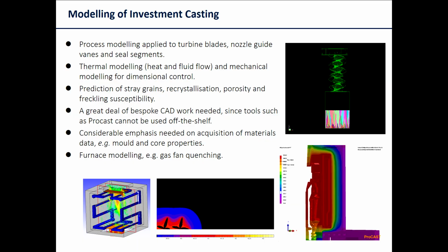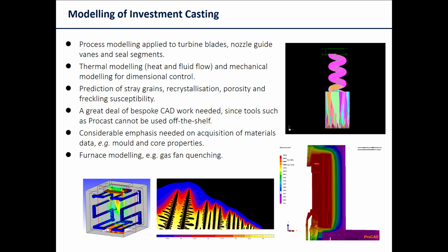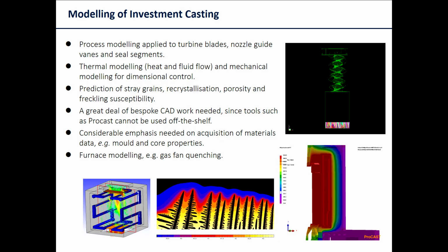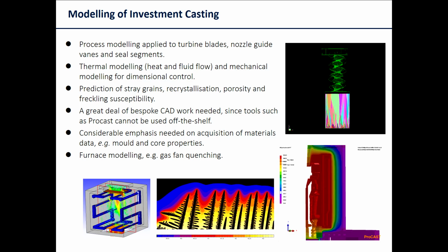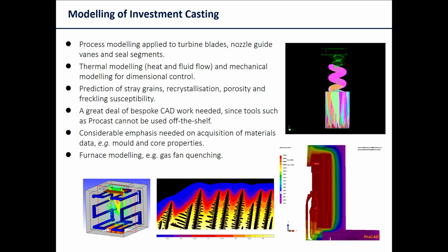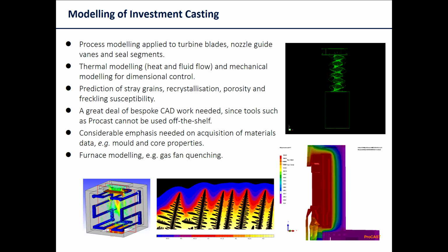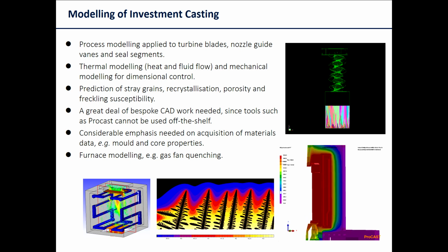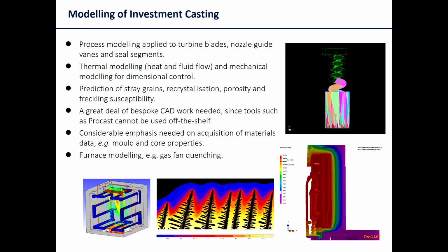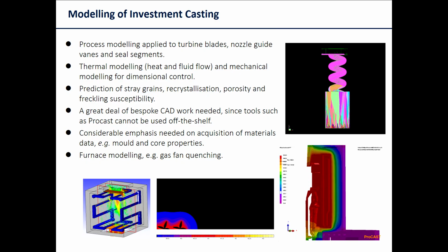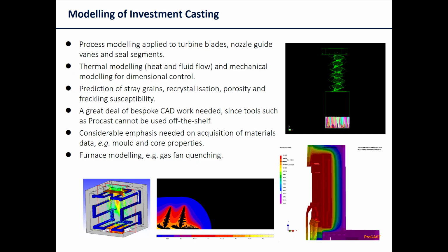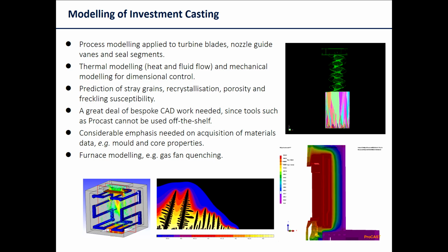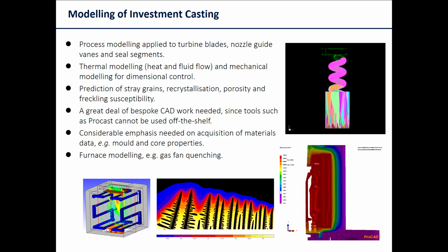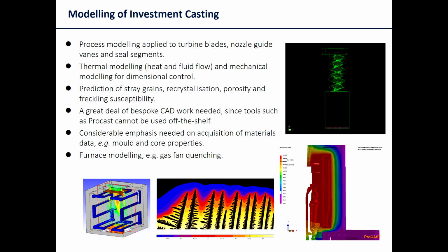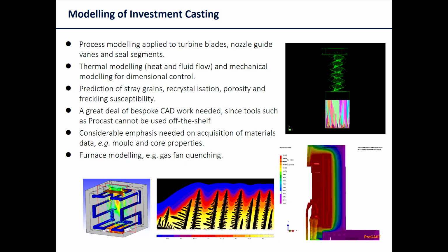But I'm going to start by just telling you some of the manufacturing processes which are used for these sorts of materials. So I understand that not all of you are manufacturing engineers, but often we cast these materials into single crystal form, and this is done typically using a seed and a grain selector here and a helical selector. And then we have a ceramic mold which is withdrawn gradually from a furnace here. We have a dendritic structure which is grown, and typically also we need to heat treat the material after it's been cast. So these are examples of computer models designed by my group over many years actually, but specifically with the idea of trying to make a digital twin for this sort of process.